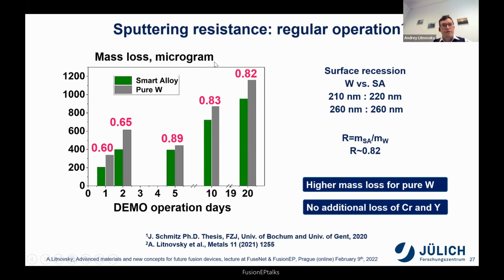If we look at the mass loss due to sputtering as a function of the fluence, which is calculated for DEMO operation, these are the fluences corresponding to 20 days of continuous operation of the power station. What we see: smart alloy is green, tungsten is gray. Smart alloy, in fact, loses less mass because of the lesser density, which is also a very good result. But important is also this red number.